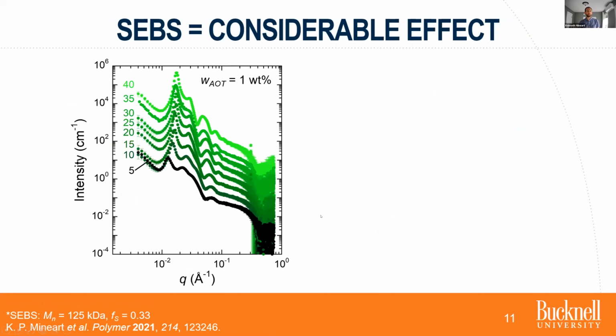All right, so then the more exciting piece to this is we can vary the triblock copolymer concentration. And this is still the same 125,000 gram per mole, 33% styrene triblock copolymer. In this case, we fix the amount of AOT in these systems. And so from bottom to top here, we're looking at 5 weight percent SEBS in increments of 5 up to 40 weight percent SEBS at the top. We can use the same model.